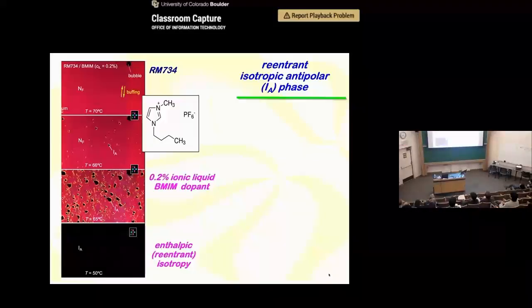So we're cooling, transition starts, these black spots appear, and then we end up with the whole sample being black. So between cross-polar and analyzer, in transmission, this is an indication that it's optically isotropic. And then once we learned this, we found a way of doing this without using the ionic liquid.